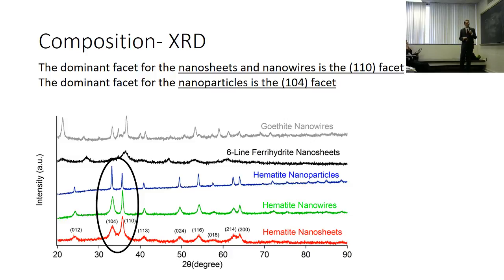So interestingly, the nanoparticles had the 104 facet more expressed than the 110, whereas the nanowires and nanosheets had the 110 more expressed. Is it important? Maybe. Find out later.